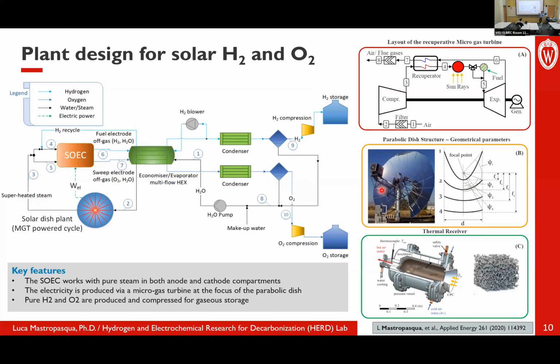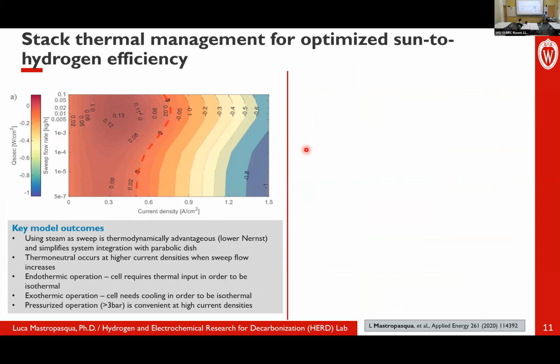Other dishes will have receivers that simply heat up the steam and supply heat to the SOEC. So the system, as you can see here, will take steam as an input and will produce two streams of pure hydrogen and pure oxygen. Then you can recover heat from the two streams using heat exchangers, and then using simple gas compression units, you can store hydrogen and pure oxygen for whatever downstream process you need.